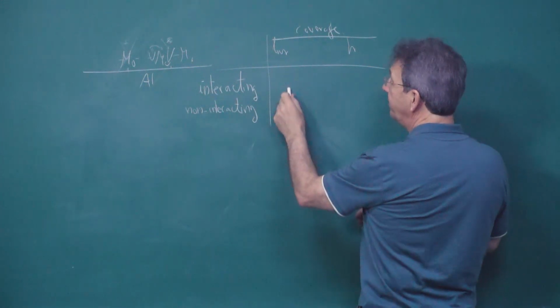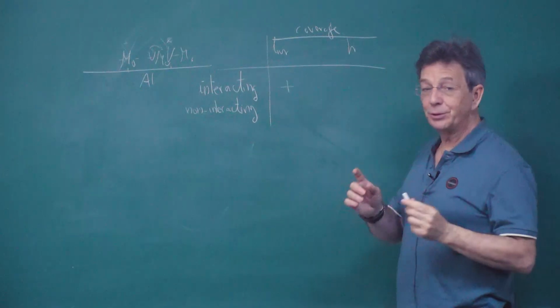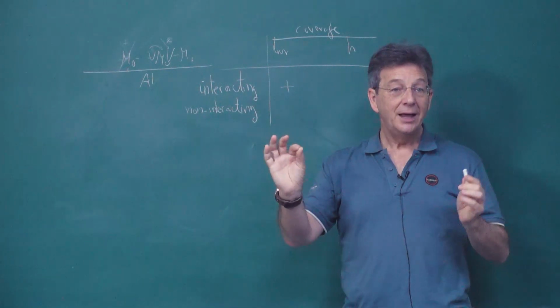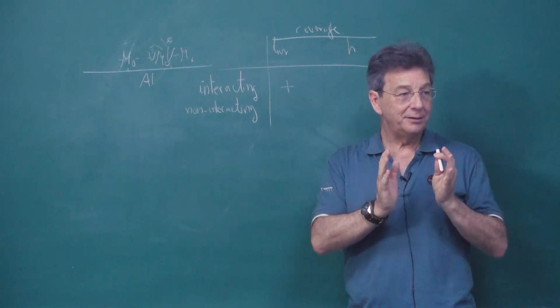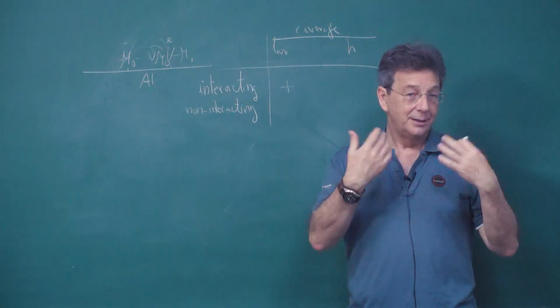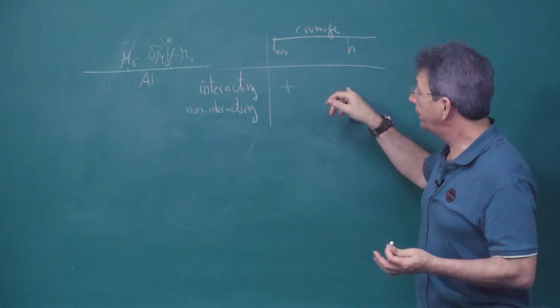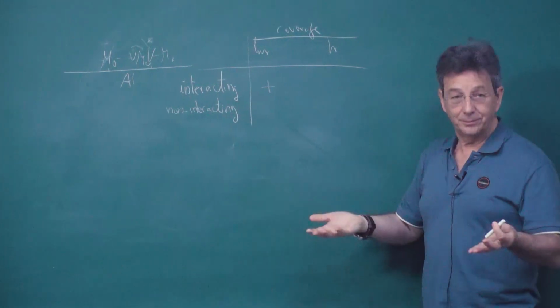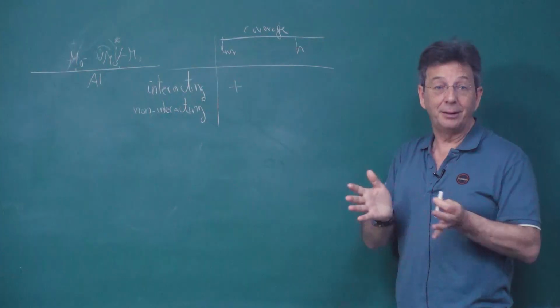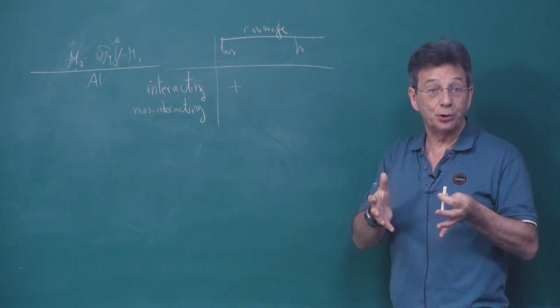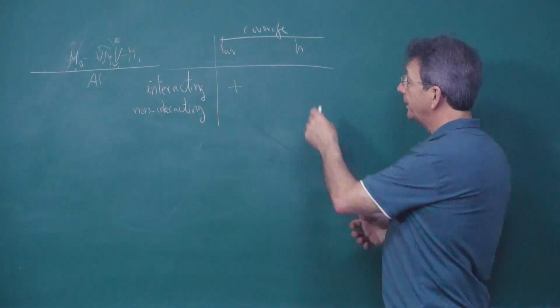So they like each other even at very low loading. Remember, like we were saying, you put a ppm of sodium, and the vanadium, the molybdenum, is affected by this ppm of sodium. So basically they are interacting. Of course, at high coverage, when you are above the monolayer, they will also interact, but above monolayer they have to interact because there is no space for them, so they have to mix.